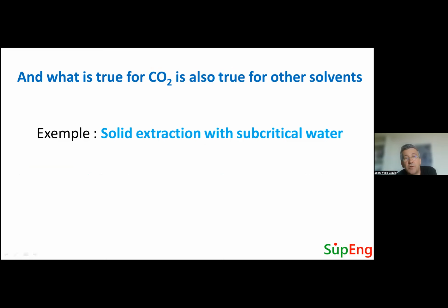What is true for CO2 is also true for other solvents. The solvent I presented is subcritical water extraction. We use water in a pressurized state to be able to increase the solubility in water of less polar compounds. So we use water at 120 degrees up to, let's say, 200 degrees to modify the solubility of the water. And this opens a range of new applications for water, basically comparable to some mixture of an alcohol with water. But again, we are faced with dilution and too high energy requirements for heating the water. And if we dilute too much, we are just not economical.